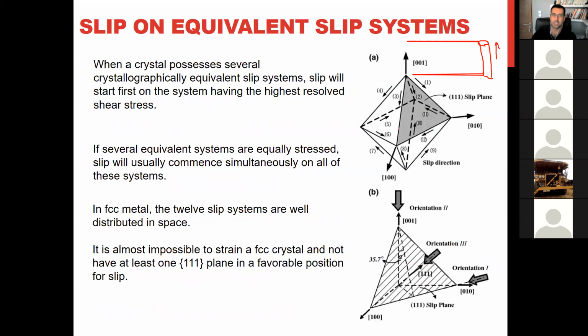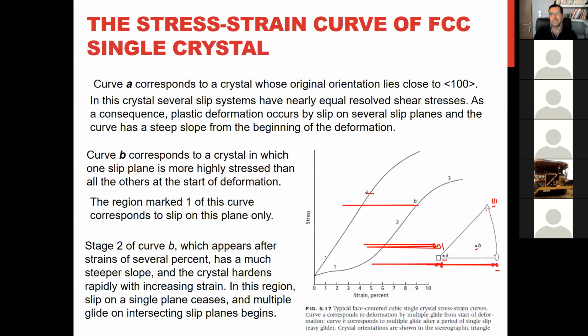Okay, so first let's talk about this direction, where we activate several slip systems together. You will see the shape of the stress strain curve is like this. When we apply load at this stress, we reach the plastic deformation, and from the beginning, the stress needed to deform more is growing, or increasing. Why? We call it strain hardening. It's more difficult to make a deformation when we do more strain.